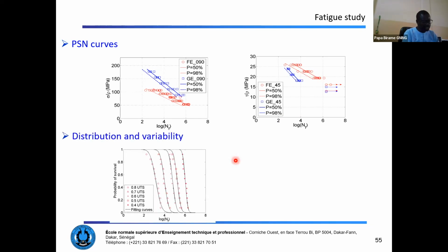So let's look at the distribution of the life cycle of the specimens at each loading level. We can see that the distribution is normal, quite Gaussian, depending on the loading level. So the left curve is the one at 80% of the ultimate tensile strength, and the other is the distribution at 40% of the ultimate tensile strength.